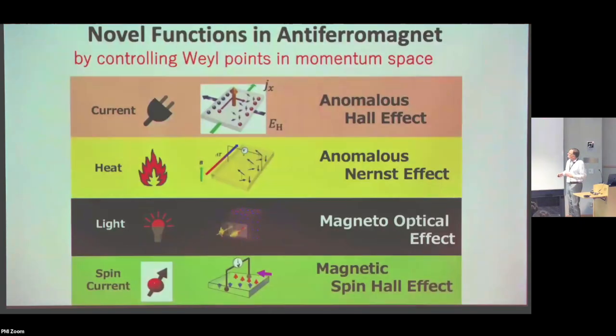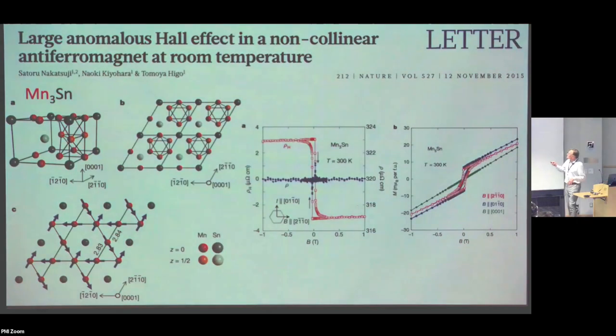Now, the structure is very interesting and, of course, important for all of the properties. It turns out that it's a stack of Kagome lattices. This is one layer, and this is manganese on the colored sites here. And then we've got tin, and this spin structure was pretty much drawn by Satoru. There were some early experiments, but it was not really quite clear what the spin structure was. But we later, and others as well, have been able to determine that this is the non-collinear spin structure that developed.